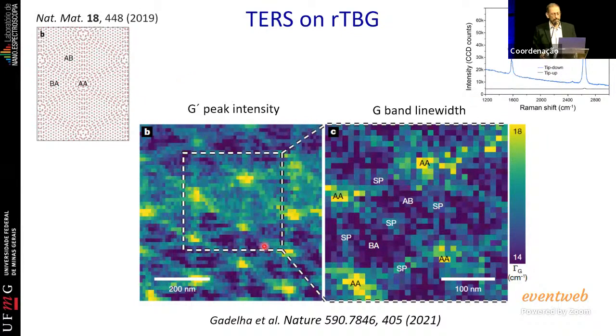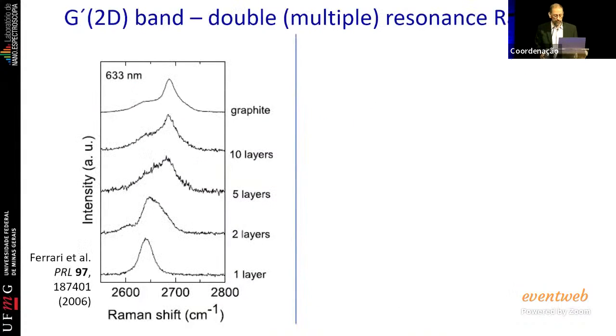For example, this information here is plotting the intensity of this peak, while this information here is plotting the linewidth, the width at half maximum of this peak. Okay, and from every aspect, you can extract a lot of information.